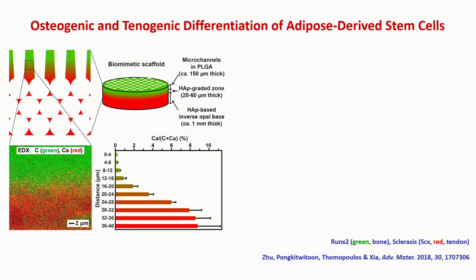So let me show you one example. This example was developed like 4 or 5 years ago. At that time, we were trying to combine this kind of scaffold with another type of scaffold we call inverse opal. It's a highly porous structure that could be made of hydroxyapatite nanoparticles. So eventually, this red region will be inserted into the bone. This gradient region will be the intersection, and this green region will basically go into the tendon. Okay, so you can suture them together.